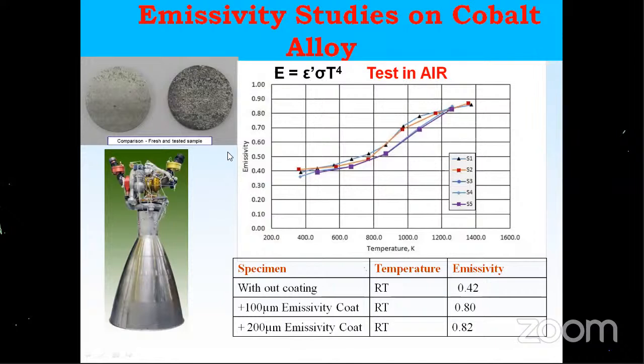So to bring down the temperature of the material, consider that the melting point of this cobalt alloy is very close to 1300 degrees centigrade, and the temperature developed inside is very close to 1150 to 1200 degrees centigrade. Imagine a shiny surface like this: the only mode of heat transfer is radiation, so the transfer will be very, very poor. But if you give an emissivity coat with 0.80 emissivity, it will approach 0.90 or even very close to 1. That means the heat transfer will be very good, and that safeguards the material.